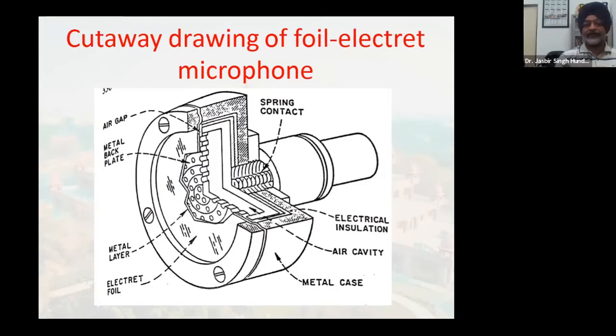When you speak, this is actually a microphone. When you speak, this polymer film moves. When it moves, there is the insulating air in between, and that gap slightly varies; it changes, right? So this microphone is able to work because there is a change in capacitance, giving rise to a change in charge, and then you have a flow of current outside. People have been working on it, especially with PVDF. It has been used to make condenser microphones, miniature microphones, and a huge number of other applications.